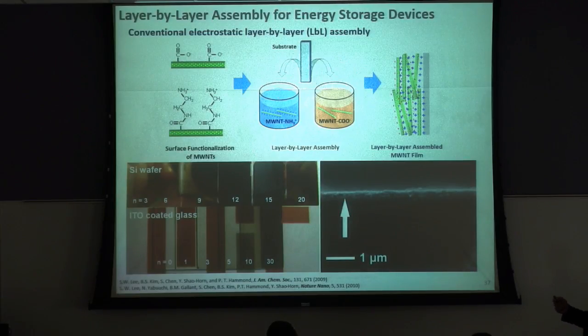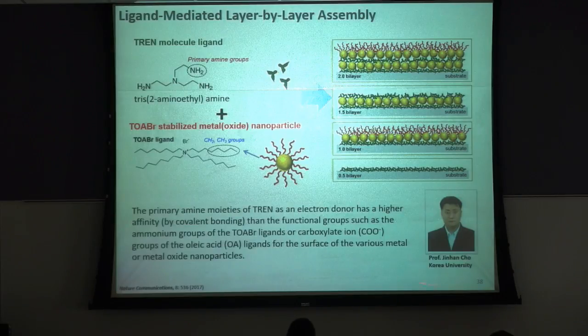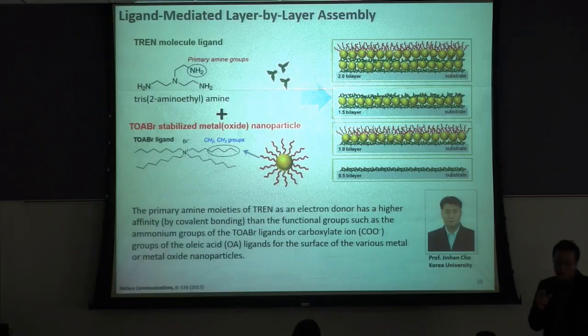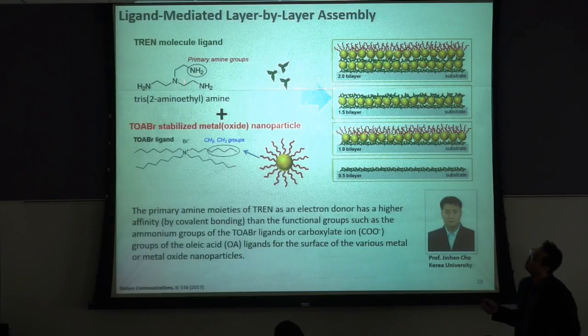So this is my PhD work at MIT. I first introduced carbon nanotubes to a layer by layer system and demonstrated some carbon nanotube-based electrodes for lithium-ion batteries. Then last year, Professor Jinhan Cho from Korea University visited my group for one year. We developed a new type of layer by layer self-assembly process called ligand-mediated layer by layer self-assembly. Instead of using electrostatic attraction here, we use the ligand exchange reaction between two organic molecules. So we prepare this kind of TREN molecule. This TREN molecule has three primary amine groups. We also prepare a different batch.